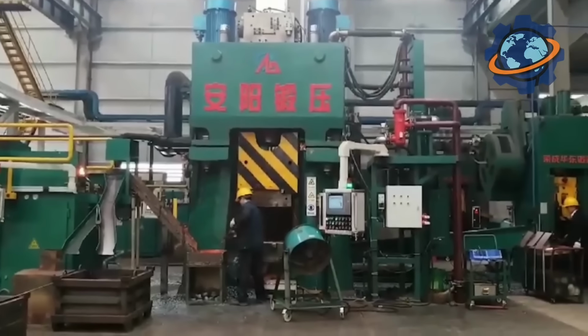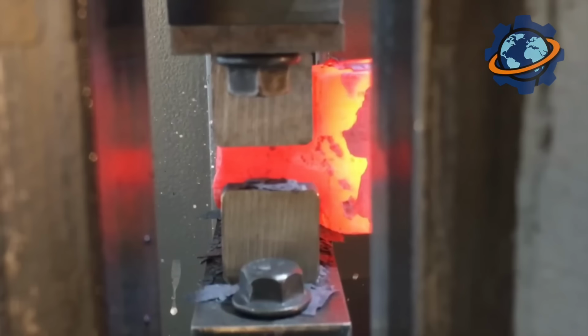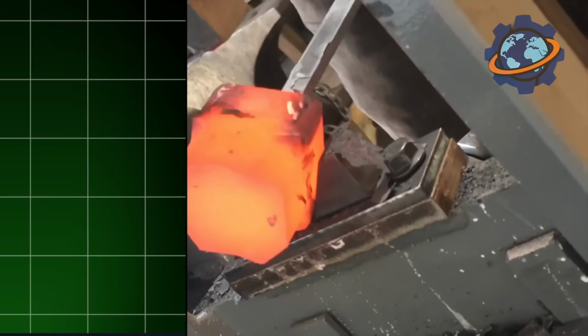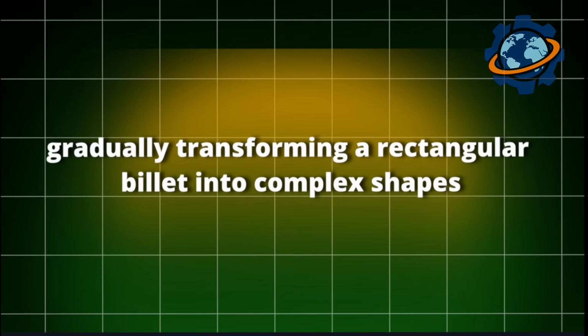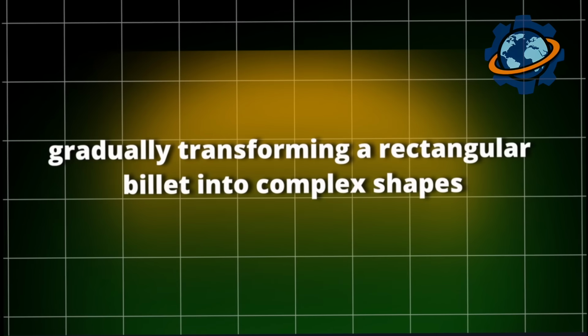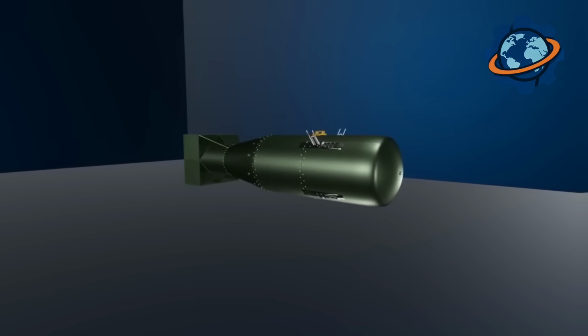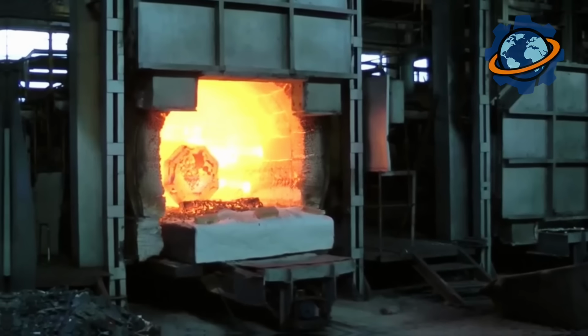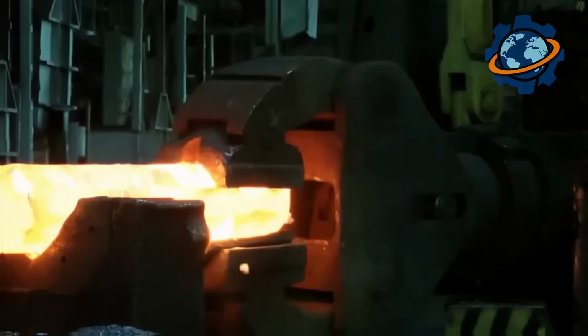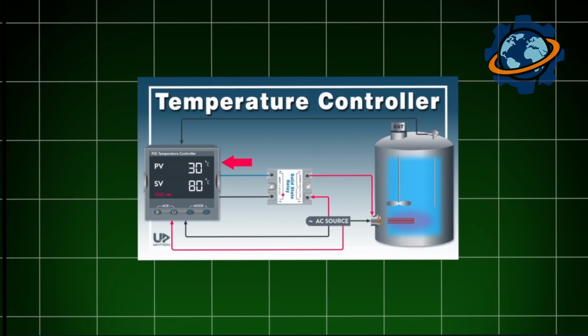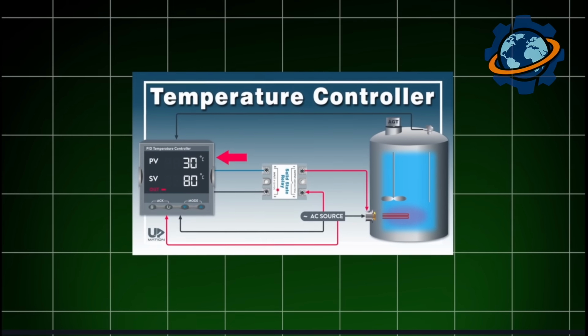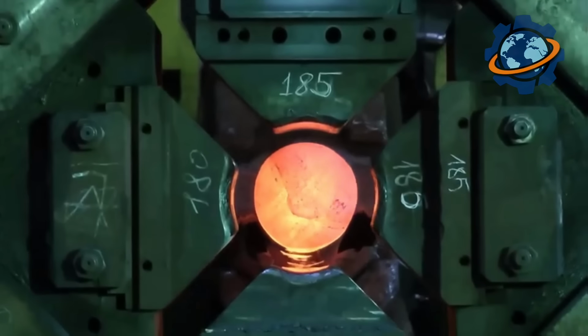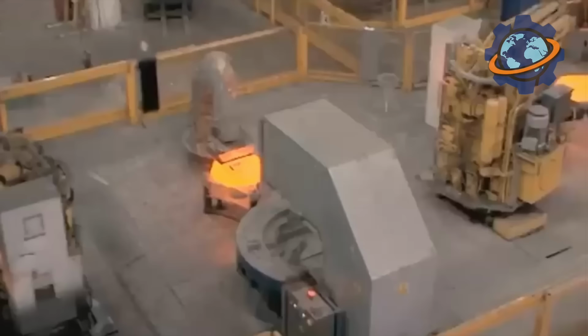Picture this: the forging process for a single large component spans 2 weeks. Workers cycle the workpiece between furnace and press 40 times, gradually transforming a rectangular billet into complex shapes: bulkheads for aircraft fuselages, rocket motor casings, pressure vessel heads. Each press cycle compresses the forging 3 to 6 inches, permanently deforming metal through controlled violence. Temperature control matters critically. Too hot, metal oxidizes excessively. Too cold, it cracks under pressure. Operators monitor color constantly, making decisions affecting millions in material value based on visual assessment of orange to red glow transitions.